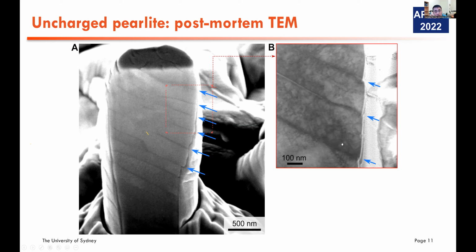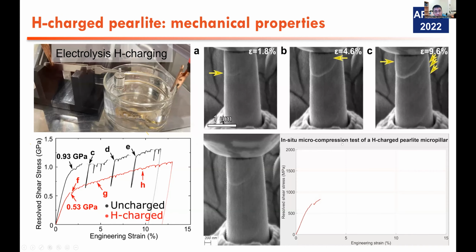After that, we characterize the hydrogen-charged pearlite. So we do the hydrogen charging on a bulk piece of pearlite, and then prepare the pillar on top of this bulk piece. Because of its bulky nature, this bulk piece is charged and serves like a hydrogen reservoir. So after hydrogen charging, we conduct a similar type of in-situ compression test, and here is the result.